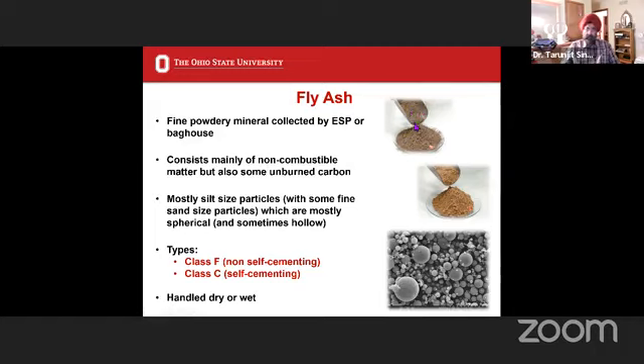Fly ash is quite an interesting material in the sense that it has the grain size distribution of silt. Okay? But the challenge you have is the two kinds of fly ashes. You have a class F and a class C. This classification strictly comes from the use of fly ash in concrete, but in general is extended otherwise. Class F fly ash is one which is not self-cementing. That is to say, if I add water to this class F fly ash, there is not enough calcium oxide available for it to harden up.